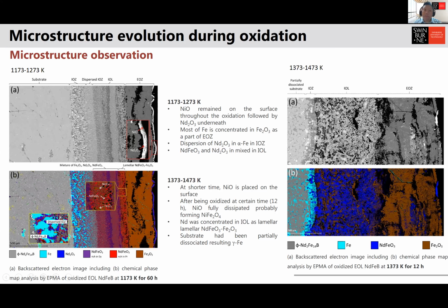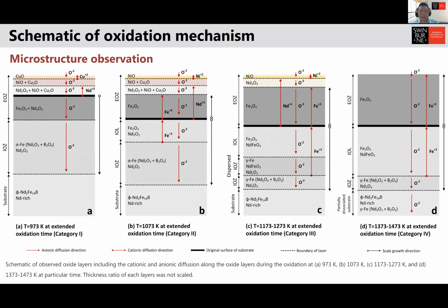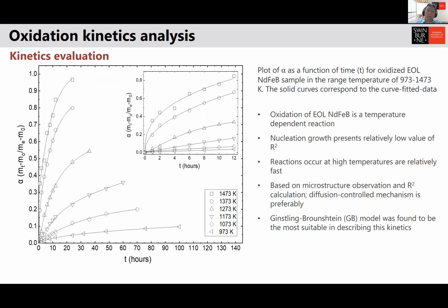Then we also try to develop the mechanisms, but I won't go into the details of this one. In a sense, at different temperature, we categorize into four. We found 4 categories of microstructure, right? Category 1, 2, 3, and 4. And it has a different microstructure evolution as well as the microstructure at the end. So we also analyzed the kinetic, and we found that we can fit this into a Ginstling-Brounshtein model, right? Common model for solid gas reaction in there.